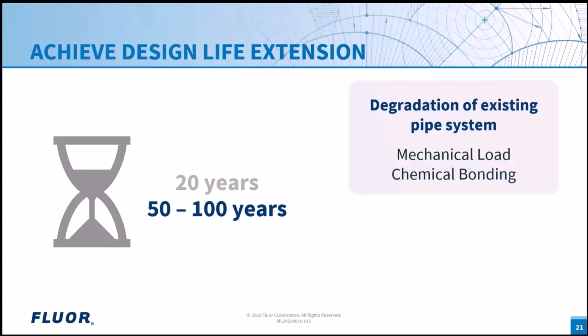Basically, there are two mechanisms for damage, or so-called degradation. The first one is a creep-like behavior, micro-crack initiation and growth of these cracks by mechanical loads, like for example pressure. The second one is the degradation of the chemical bonding between the glass and resin by, for instance, water ingress or diffusion into the laminate. Knowledge about this is limited at this moment, and the degradation mechanism will not be activated instantaneously. Furthermore, the rate of degradation is also an unknown parameter.